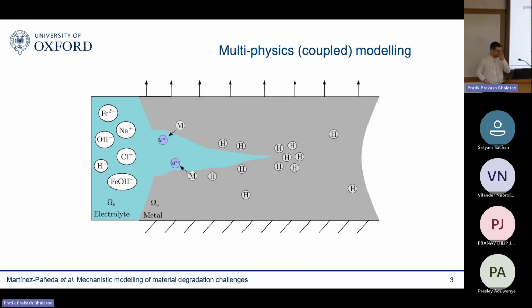The first one is coupled multi-physics modeling. So if we think of a general stress corrosion cracking problem, you have something like this. You have some sort of metal that has been subjected to mechanical loads, which contains some sort of defect. It could be a pit, a crack, any other defect. That is exposed to an aqueous electrolyte where there are multiple ionic species that are moving around due to fluid flow, due to electromigration, due to diffusion.